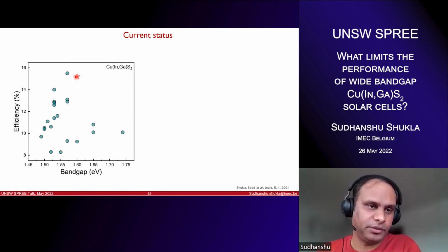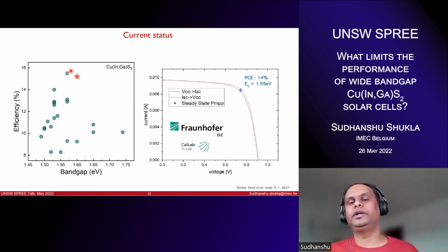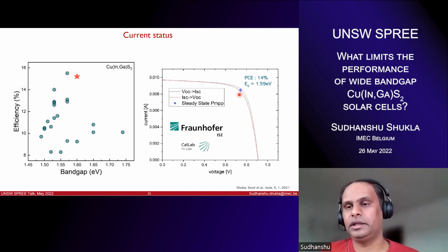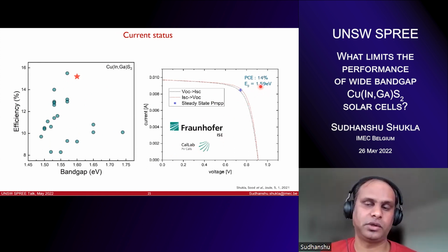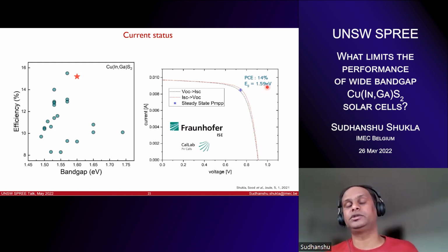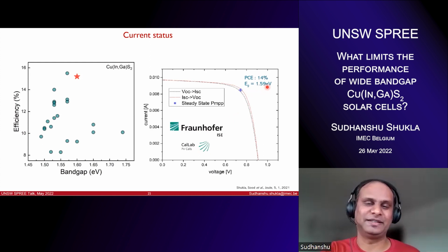So from the efficiency perspective, it puts us somewhere here. These are all the points taken from the literature. And this absorber of 1.6 eV puts us somewhere here. And this particular efficiency that you see right here is from Solar Frontier, the record absorber, so to say. And we have also gone on to certify our cells. So this is one cell that we certified from Fraunhofer ISE, which was about 14% with close to 1.6 eV band gap. So that's very encouraging. So we not only have absorbers in the lab that are quite efficient, we can actually certify them. And this is where we are at the moment, 14%.